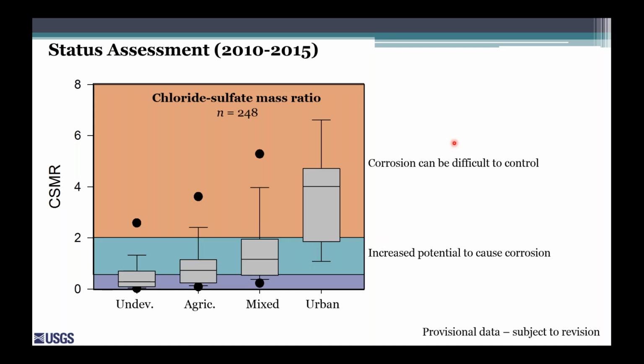And also, if you remember from a few slides ago, a chloride to sulfate mass ratio less than 0.5 is associated with a low potential to cause corrosion. And above 2, it can actually be difficult to control corrosion through traditional means in water distribution systems. The urban areas from this study had mean and median chloride to sulfate mass ratios well above 2, indicating a high potential to cause corrosion.